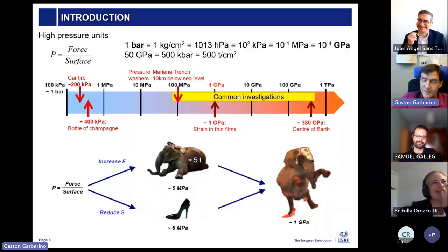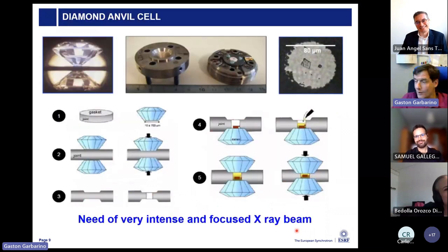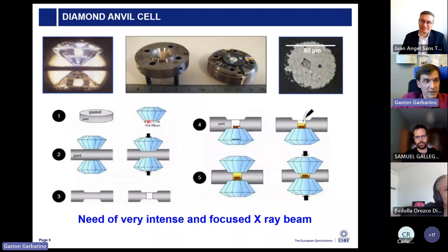But the problem is to keep them flat, because they can get thin. That's why we have different apparatus. The one we work with every day is the diamond anvil cell, in which we have two diamonds, like the ones we use in jewelry, but with a polished tip at the border. Then we confine a region in a gasket. That is what we consider a pressure chamber, and the sample lives there inside with, and close to it, a pressure marker that allows us to measure the pressure.